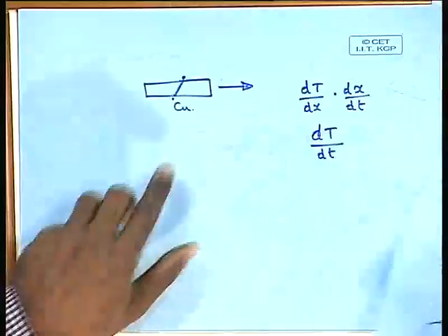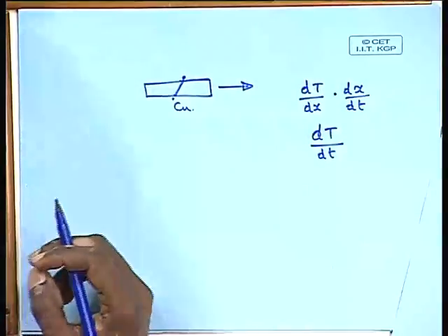And what is the temperature at the bottom? Temperature at the bottom is the room temperature, which is that of copper. Copper is always water cooled to some extent. Sometimes people do it by water cooling, but most of the time copper itself has such a high thermal conductivity, you don't need to cool it. Okay, so the copper is rotating at very high speed with a high thermal conductivity, and because of which you can have a fast cooling.